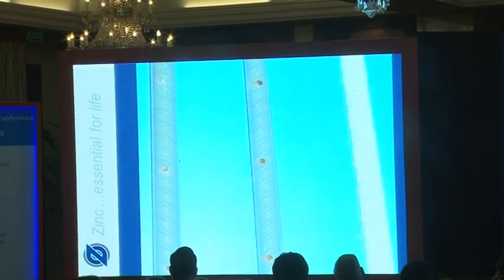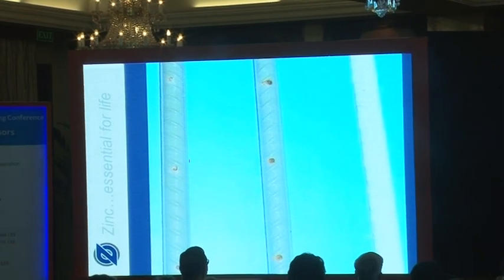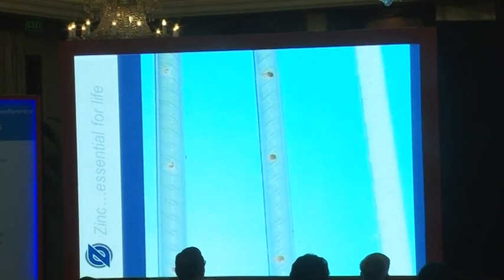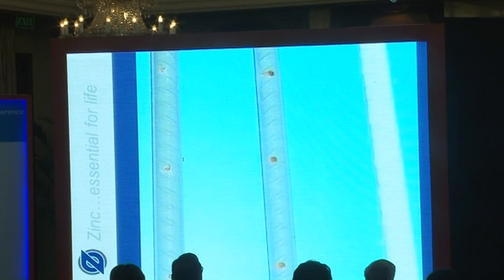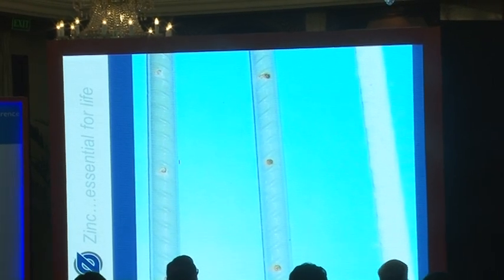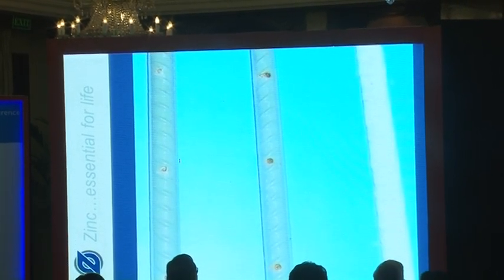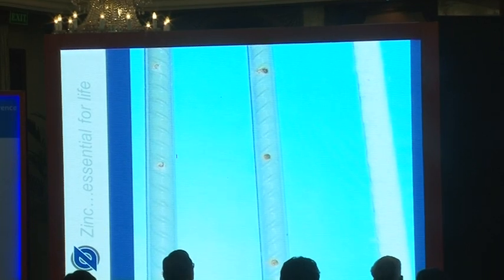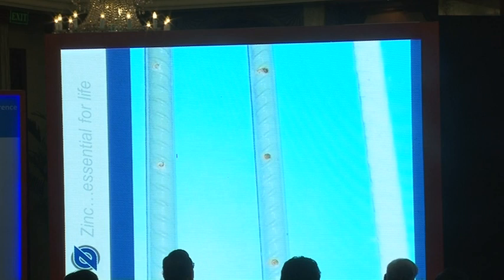On the very right-hand side, you see the zinc only. So this is the continuous galvanized rebar with about a 20 micron coating thickness in this case. After 24 hours, there's no red rust. It's all white rust. All zinc corrosion products are white. So that's what zinc corrodes, it looks white. There's no red, there's no steel attack.